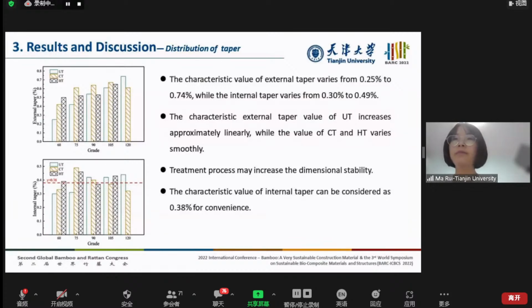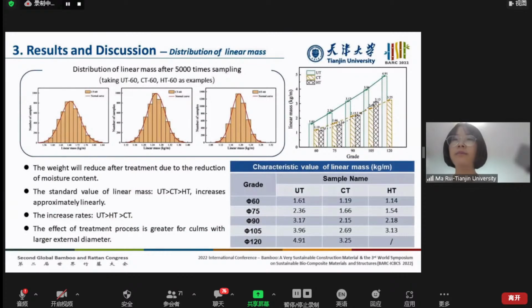0.38% for convenience. For the distribution of linear mass, the value of UT is higher than CT and HT, illustrating that the weight of moso bamboo culms reduced after treatment due to the reduction of moisture content. With the increase of grades, linear mass increases approximately linearly. The increase rates of CT and HT are slower than that of UT, proving that the effect of treatment process is greater for culms with larger external diameter.